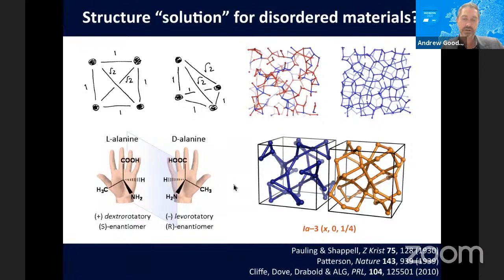But even single crystals are not immune to this. A very obvious example is the case of 2 enantiomers of a single crystal, which have exactly the same set of 3-dimensional pair correlations. And of course, this comes down to the fact that the Patterson function, and indeed the scattering pattern itself, has inversion symmetry. There are sneakier examples.